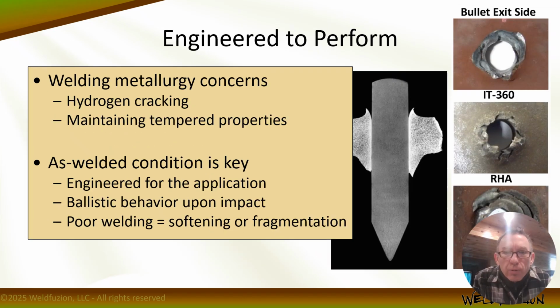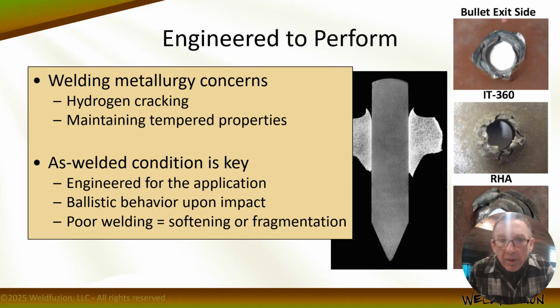So these materials are engineered to perform using metallurgy by alloying specific elements together, by heat treating and creating certain properties, and then by tempering to restore some ductility to that strength. And if you look at the pictures on this slide, it shows the exit area, right? The backside of what can happen if we embrittle the microstructure, which also creates a condition where hydrogen cracking could occur. So something that we're going to be paying attention to are the conditions that exist that are prone to hydrogen cracking, right? We have sufficient carbon or alloy content. These things are going to behave like a high carbon steel. We have a susceptible microstructure. I mean, these materials are provided in a tempered martensite, so we already are dealing with a susceptible microstructure. In many cases, we have joint restraint, right, where we're fixturing these things or holding them in position. And the need to control hydrogen and cooling rate exists.